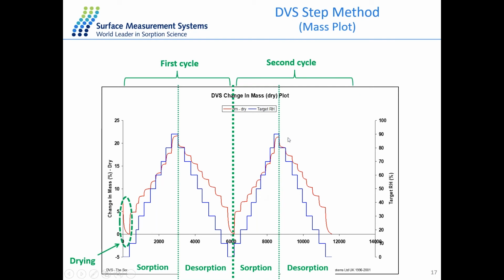And this time, as you can see, the second cycle can go up to the same level as the first cycle and go back at 0% RH to 0% mass change. That means this moisture sorption for the rice starch sample is a perfectly reversible process. There is no water molecule trapped inside the material at the end of the desorption steps.